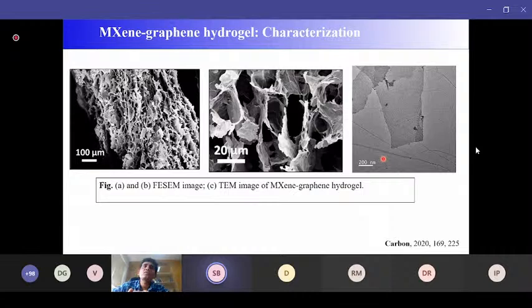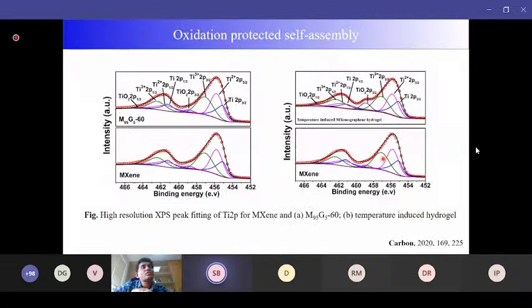So we have successfully made the MXene and graphene hybrid hydrogel, where the MXene content is around 95% and the graphene content is around only 5%. And this graphene mainly gives us structural stability, because most of the property will come from the MXene, because MXene makes up 95% of it.